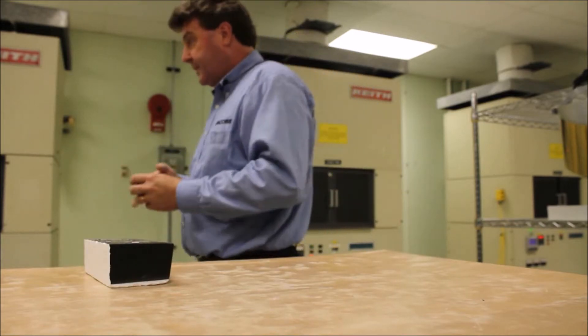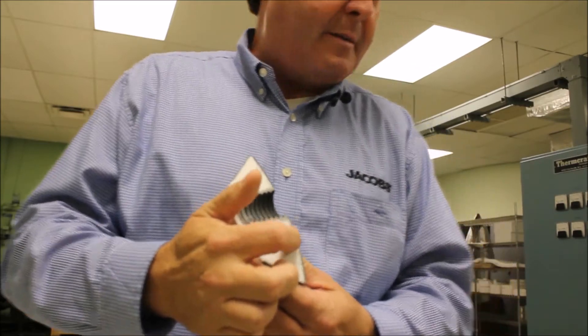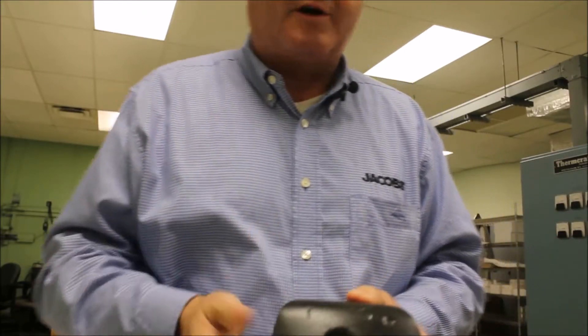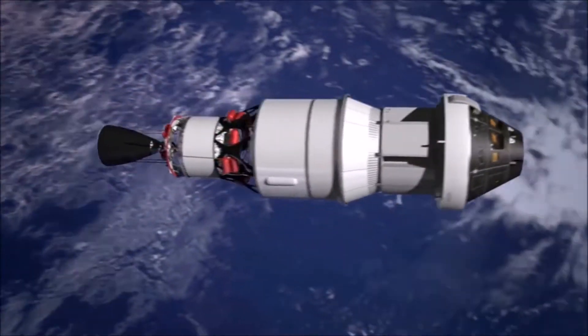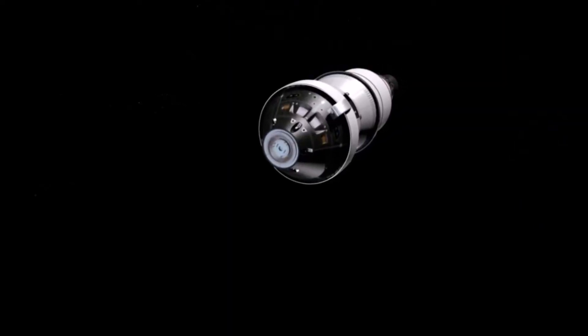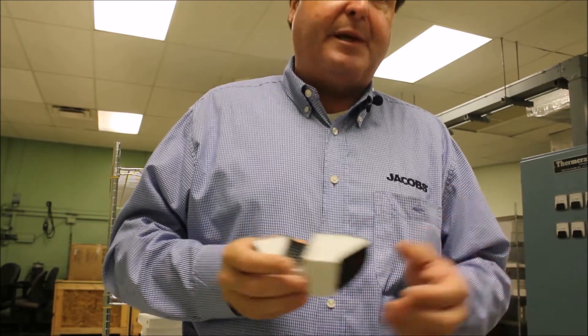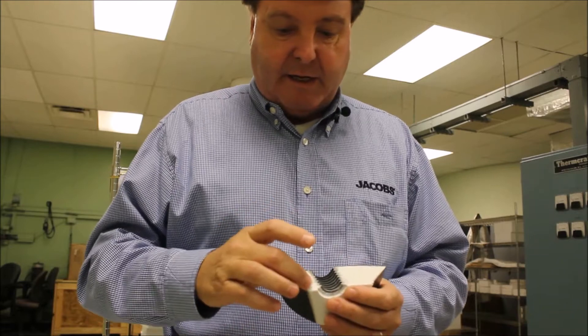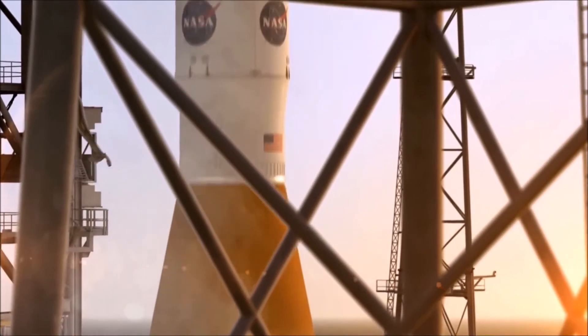Now we've moved to a different coating system. You can see a section through a tile here where the coating is quite a bit thicker. It doesn't add very much weight, but it is significantly tougher — I can't really damage this without the help of a screwdriver or a key. One of the prime advantages, and one of the reasons they used it on the Orion for its deep space purposes, is micrometeorite resistance. Space is full of MMOD particulates which, traveling at very high velocities, can do very significant damage. During the development of the TPS for Orion and Ares before it, they realized that these tile coatings, in combination with the tile base material, have extremely good micrometeorite resistance.